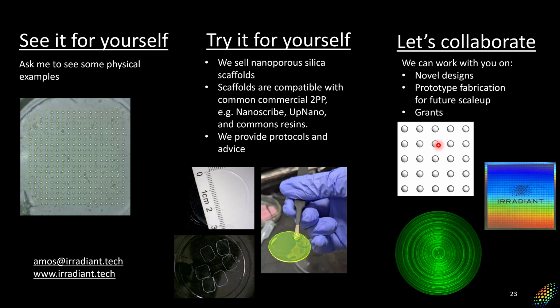To answer the question about coating the scaffold, no, currently, at least with the silica process, you can't really coat that because there is shrinkage in the process of making it. So typically we make them freestanding and then attach them down onto things. There is, with the process of porosifying silicon, if you have a wafer or grow a layer of silicon, you can then porosify that and use that as a substrate.